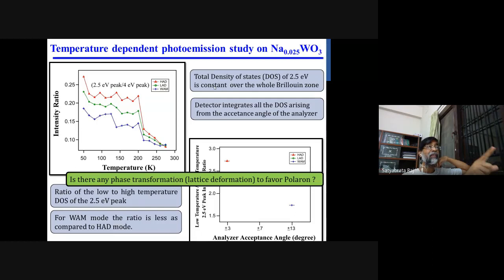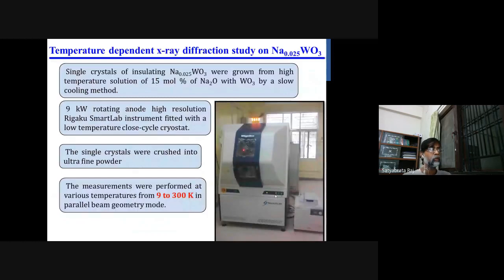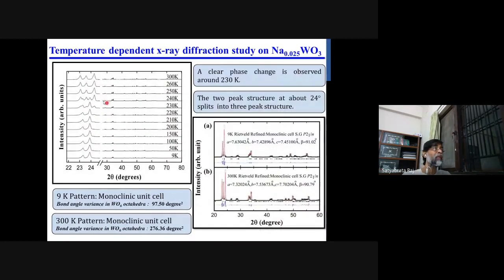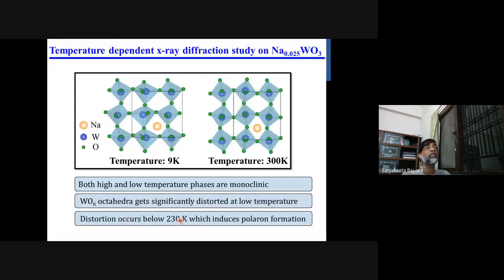So is there any lattice deformation around 230 Kelvin in this sample, so that polaron formation will be favorable? To understand this, we did low temperature XRD, and we collaborated with Gautam, and we measured from 9 Kelvin to 300 Kelvin. We found that at 230 Kelvin a new peak develops in the XRD spectra, and this shows that WO6 octahedra gets significantly distorted at low temperature, and the distortion occurs below 230, which induces polaron formation.